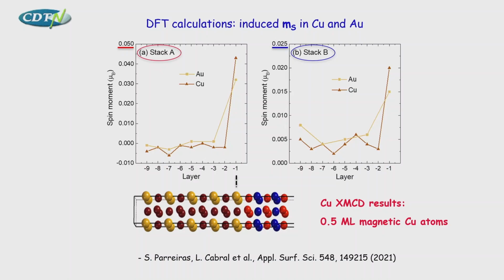Then the calculations indicated that the magnetism seen by XMCD is due only to the copper atoms that are at the very interface. That means the signal is from half a monolayer of magnetic copper at the very interface. Okay?